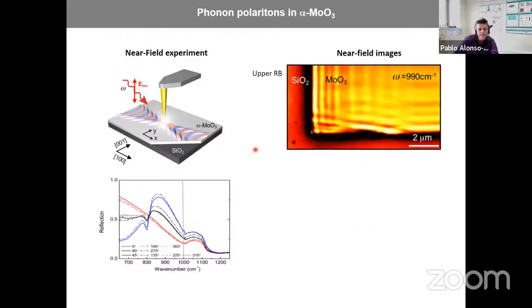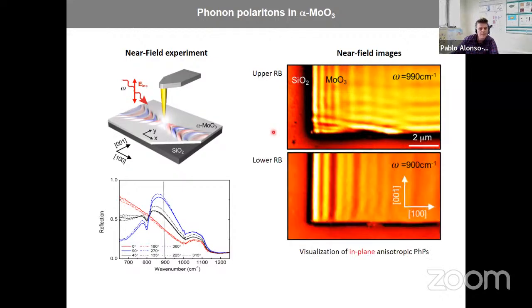Okay, so we measured here at some frequency where we saw a peak of the reflection spectra. So we thought that there were some phonon polaritons to be excited, and then we saw this. They look more or less isotropic because the wavelength is the same here as here. These fringes are the polaritons propagating. And then we measured here in this other band where the reflection was large.